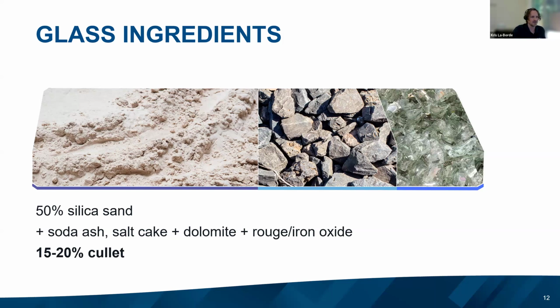Most companies, including Guardian, can fully recycle low-E coatings as part of that cullet batch, and it can be in-house glass that didn't make it to the end of the line. It's broken up and recirculated into the kiln, or it can be post-consumer. They have to follow strict procedures, but the post-consumer cullet percentage is growing and growing and growing. It's estimated that for every 10% cullet you use in a batch, you lower your energy demands by about 3%. So it's very, very important.